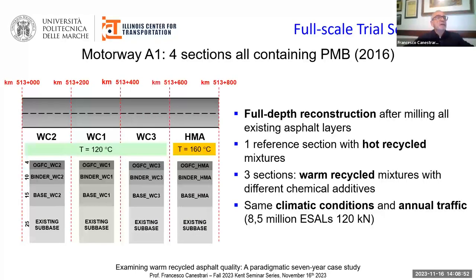The next step was the construction of the trial section along the motorway A1 in 2016. The project involved the full depth reconstruction of the pavement after milling all existing asphalt layers for a total length of 800 meters. As shown in figure, a reference section was built with hot recycled mixtures and compared with three sections built with different types of warm mix asphalt chemical additives. All sections coded as WC2, WC1, WC3, and HMA are characterized by the same conditions in terms of pavement structure, subgrade, traffic, and weather conditions.